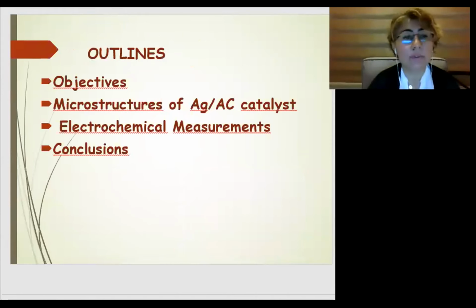In my presentation, I will explain my objectives, the microstructural characterization of the carbon-supported silver catalyst, and the electrochemical measurement of the catalyst. At the end of my presentation, I will give my conclusion about the study. The silver deposited carbon catalyst prepared by electrodeposition method was examined for the redox process and electrocatalytic activities during the oxidation of methanol and sodium borohydride in alkaline solution. The catalyst was characterized by X-ray diffraction, energy dispersive X-ray analysis, and scanning and transmission electron microscopy. We also use electrochemical voltammetric analysis.